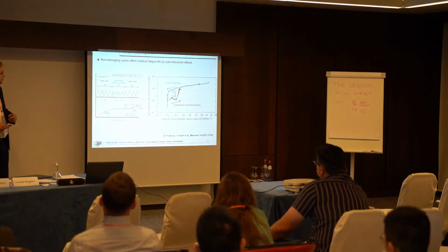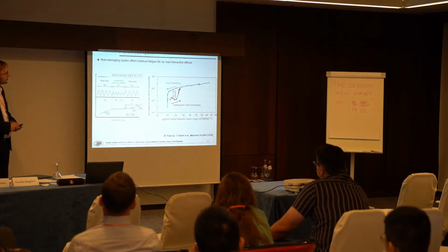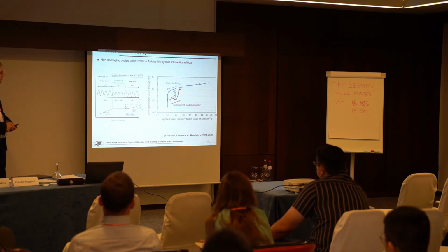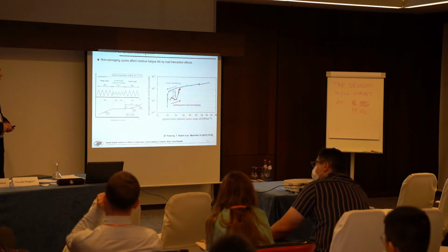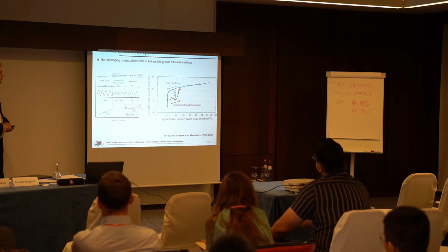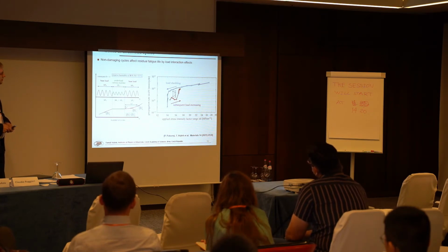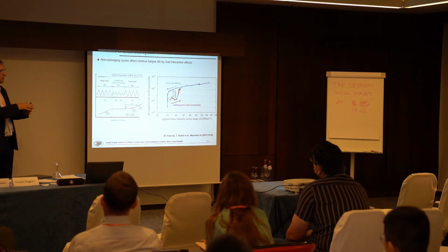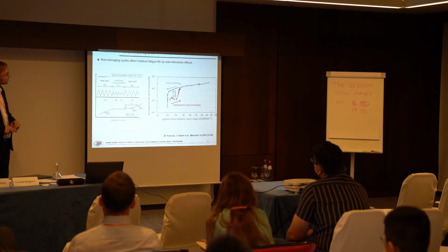Also, there's a loading history effect. For example, if you apply the delta K decreasing method for measurement of threshold, you go down this blue line, and after you measure the threshold and you want to go up again with the loading, you will not go along the same line. You will go to the red line, because at very low crack growth rates, a large amount of oxide debris was produced at the fracture surfaces and increased oxide-induced crack closure. So then you need to apply larger delta K in order to repropagate the crack, and after you propagate out of the influencing area, you get back to the original curve.